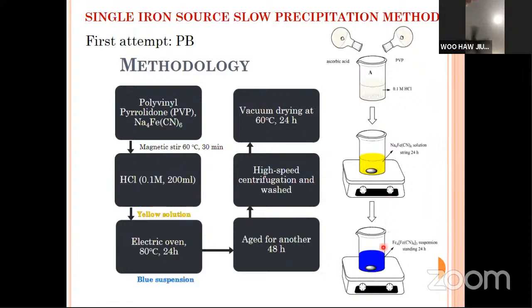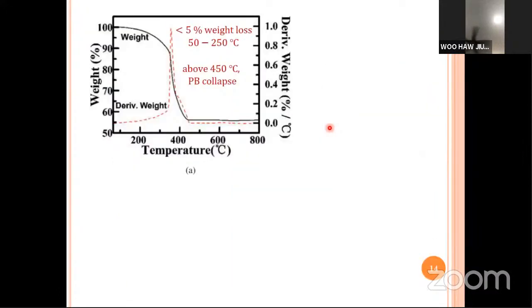We obtain a blue suspension. Then we continue to age it for another 2 days, 48 hours. Then we collect it using high-speed centrifugation, and then we wash it. After that, we vacuum dry it for 1 day. With the obtained Prussian blue powder, we send the as-prepared product for TGA. This is what we obtain.